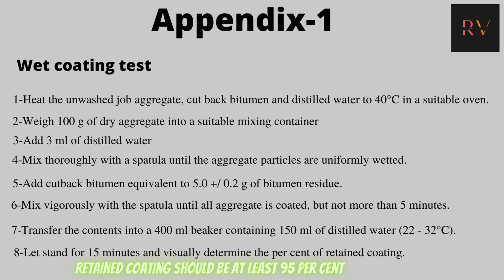Add cutback bitumen equivalent to 5 plus or minus 0.2 gram of bitumen residue. Then mix this vigorously with the spatula until all aggregate is coated, but not more than 5 minutes. Now transfer this content into a 400 ml beaker containing 150 ml of distilled water, which should be around 22 to 32 degrees Celsius. Let it be there for 15 minutes and visually determine the percentage of the retained coating. The retained coating should be at least 95%.